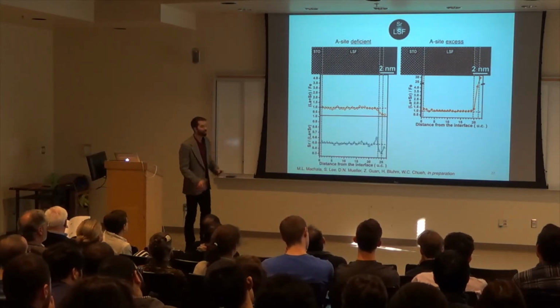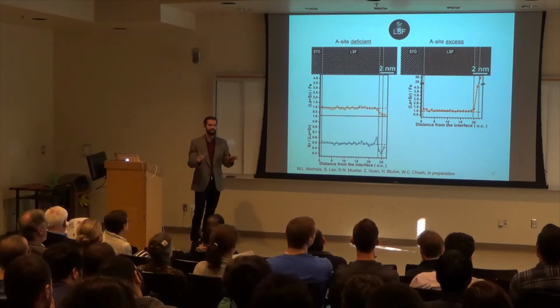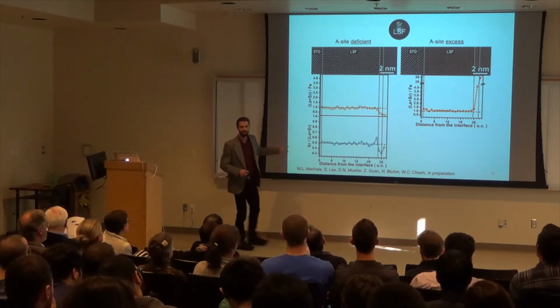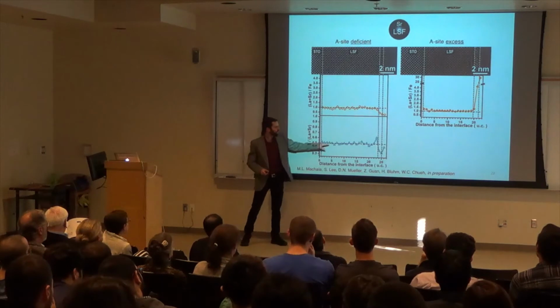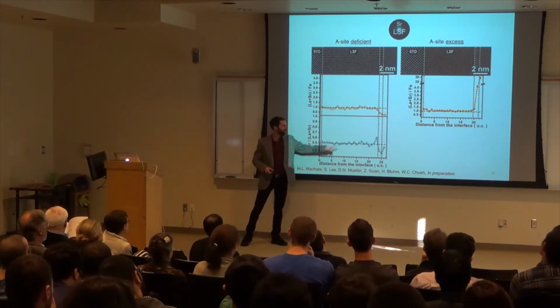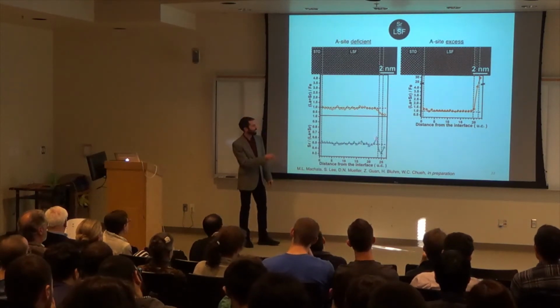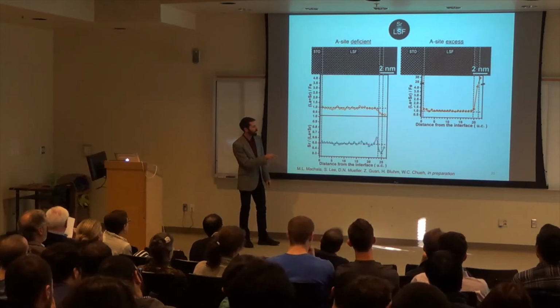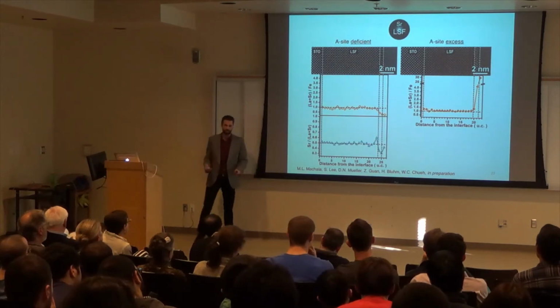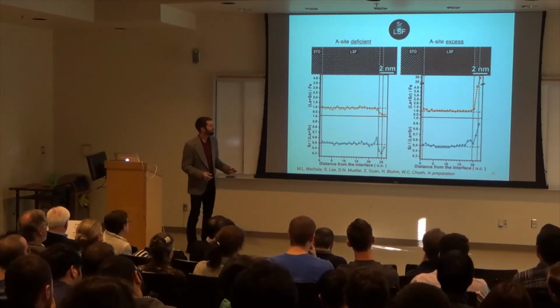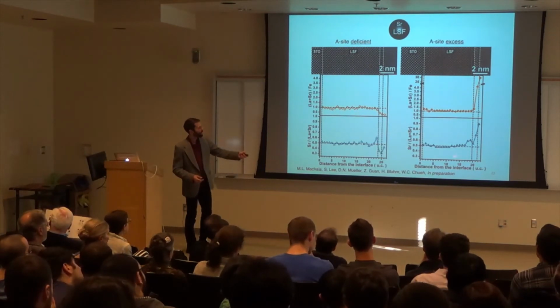Now, if we focus in on just the A site, nothing to do with iron, just the A site, when we look at how much strontium is in there, we see that it's relatively constant in the bulk, but it deviates here, right at that cation double layer, showing us that there's some segregation present. And then when we move out to the other sample, we see a similar trend right here.